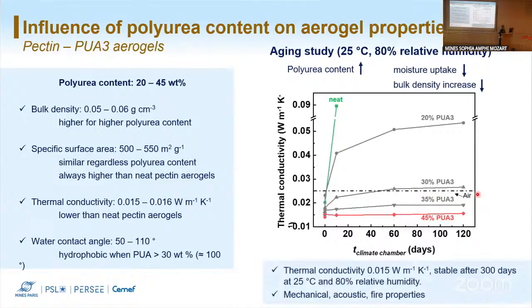So for these materials, the thermal conductivity was 0.015 watt per meter Kelvin, and we have an extended study than this, and we see that it's stable after almost 300 days. And since they were the most promising materials, we tested also mechanical, acoustic, and fire properties. Very first results that I don't have time to discuss with you in the presentation, but they seemed very interesting and promising.